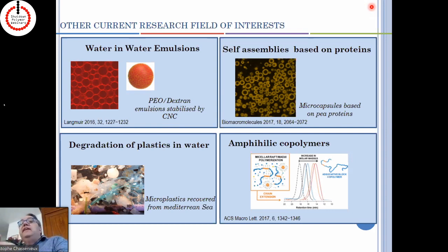So the funny thing is that each step is very rapid. The exchange of one surfactant molecule from the wormlike micelle towards the water is very, very fast. But if you want to measure the relaxation time of the overall self-assembly, it can take a lot of time to reach thermodynamic equilibrium. In our case, we have seen that sometimes you need to wait 1 or 2 days before having a system at equilibrium, even if the relaxation time of the exchange is very fast.